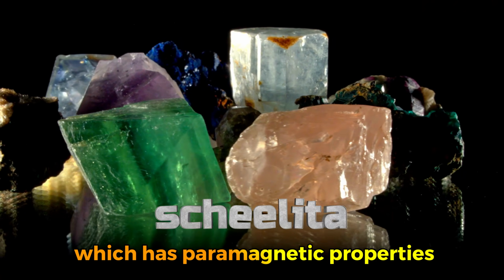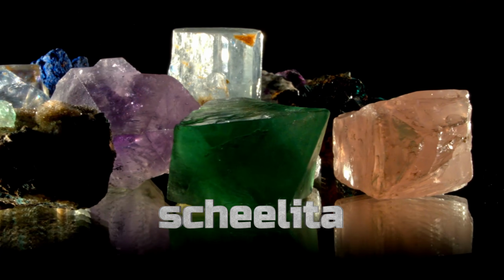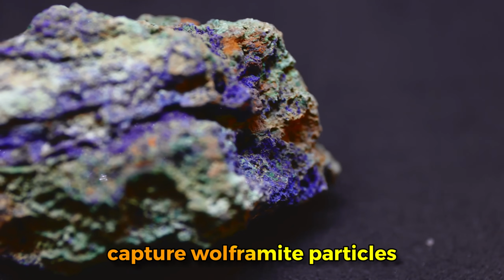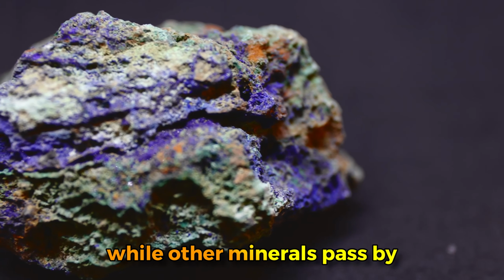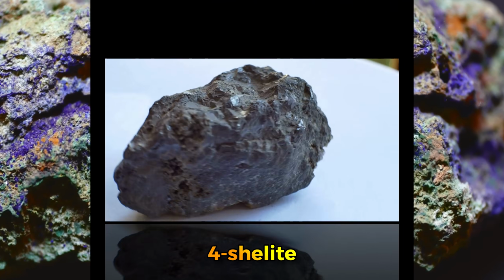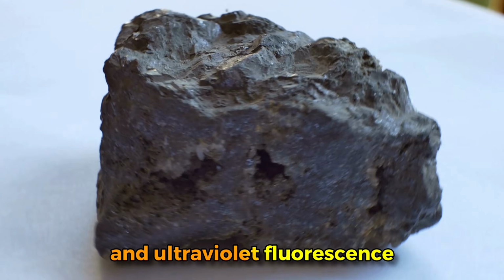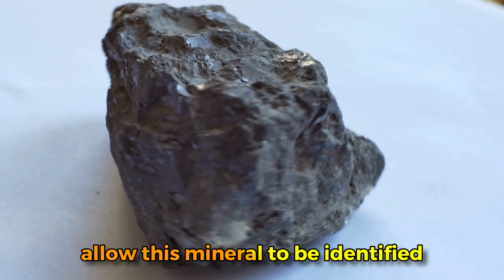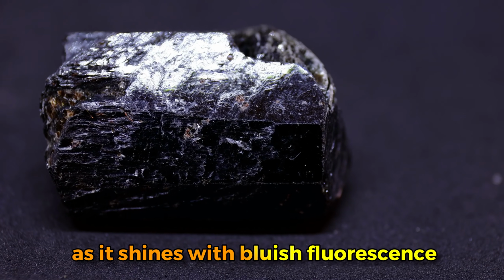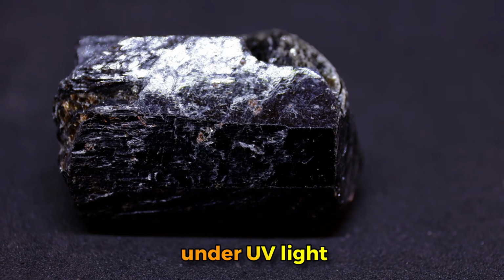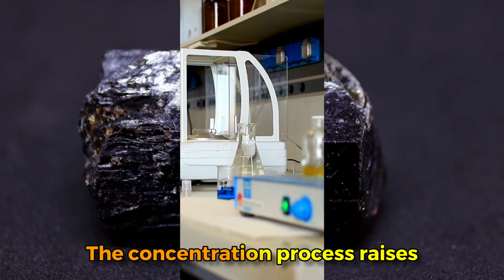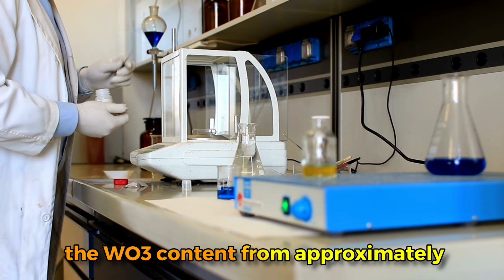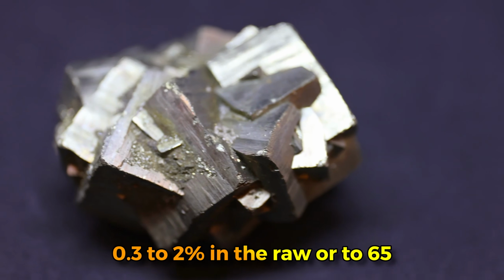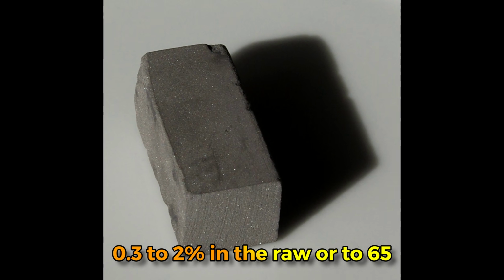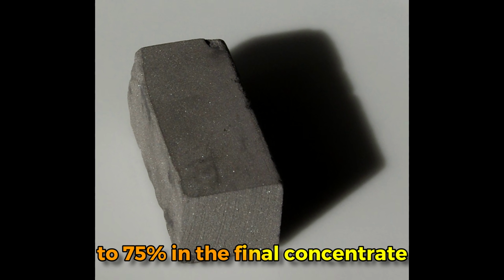Magnetic separation is also effective for Wolframite, which has paramagnetic properties. Medium-intensity magnetic fields capture Wolframite particles while other minerals pass by. For Scheelite, electrostatic separation and ultraviolet fluorescence allow this mineral to be identified and separated, as it shines with bluish fluorescence under UV light. The concentration process raises the WO3 content from approximately 0.3 to 2% in the raw ore to 65 to 75% in the final concentrate.